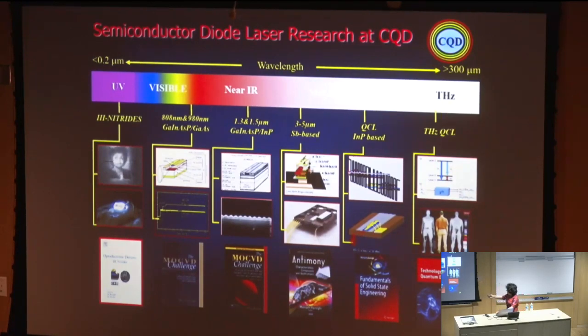Okay, now we are coming to the infrared part. Infrared has two approaches: interband or intersubband. Interband uses the minority carrier, meaning electrons and holes combine with each other in the active layers, and the emitting wavelength, or the absorption of the detector, is related to the energy gap of the semiconductor material. But when you go to very long wavelength, the energy gap becomes very small. kT is only 25 millielectron volts. So in this case, we go to the intersubband, using what? Superlattice.